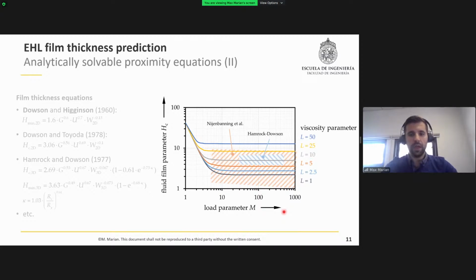Generally, there have been several variants developed and published over the years, mostly to cover, for example, a wider range. When we compare, for example, the equations that have been suggested by Nijenbanning in comparison to Hamrock and Dowson, which have been derived for data in this range, mostly they have been developed to cover wider ranges than the initial equations, and also to be valid, for example, in the more isoviscous and or the rigid regimes. And to describe non-dimensional groups and parameters or the film thickness equations, basically they can deliver quite reasonable agreement with many lubricants that was experimentally verified by various authors, for example, by interferometric film thickness measurements.